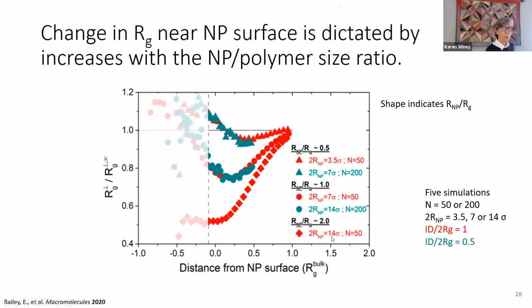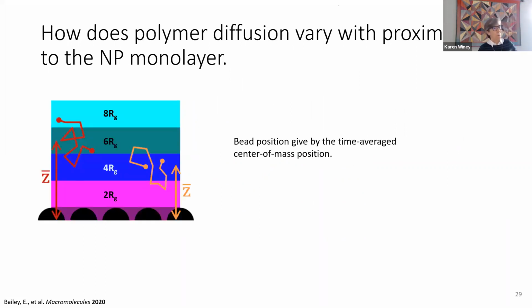And these distortions, once you get up to this very large nanoparticle relative to the RG of 2, we have a distortion of about 50%. It's compressed by 50%. And all this chain conformation distortion only persists out about an RG. Okay, that's important because what we're going to see is the disruption in polymer diffusion is on a much longer scale than the chain conformation. Okay, so on to polymer diffusion.